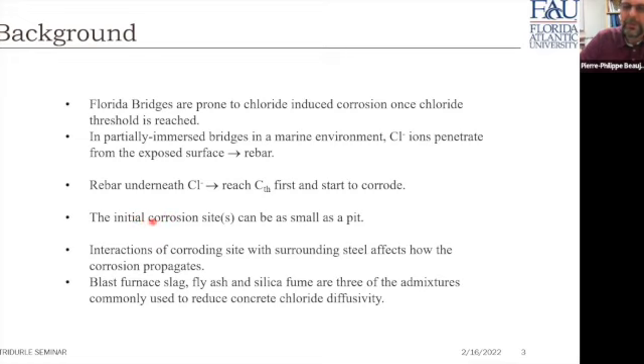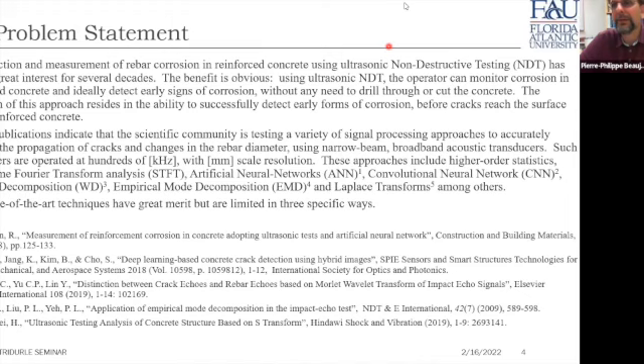What is important, however, is that the initial corrosion sites can be as small as a pit, and interactions of the corroding site with surrounding steel are going to affect how the corrosion propagates. The result, if not handled, can be significant damage in the reinforced concrete, with literally pieces of reinforced concrete falling off in the water. There are techniques to mitigate this using blast furnace slag, fly ash, and silica fume, which are three of the admixtures commonly used to reduce concrete chloride diffusivity. By admixtures, we mean that when the concrete is mixed, materials like blast furnace slag are added to the mix.